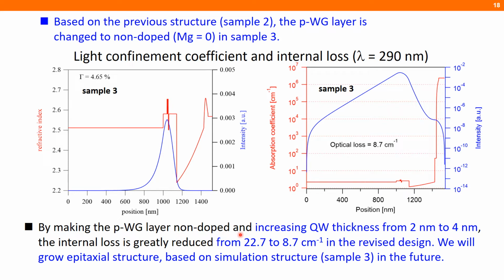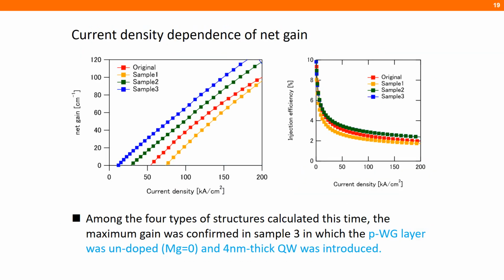So in the near future, we would like to use this new improved structure for the laser diode, and probably we can get the lasing. So we are just one step behind lasing. Here is the current density dependence of the net gain. So here is the net gain and current density. The original sample, which I showed, was here, but later the simulated one without magnesium-doped P waveguide layer shows very high net gain. So we will use this configuration in the near future.